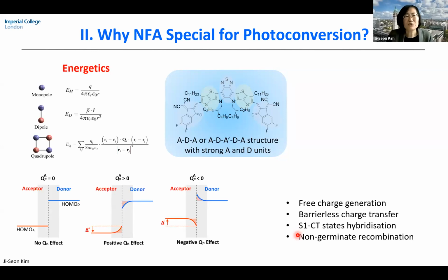But I would like to consider two main things for why this Y6 is so special. First of all, in terms of its energetics, as I mentioned before, these molecules, particularly with symmetric structure, have a negligible dipole moment. But because of the strong donor and acceptor character, we still have a very high quadrupole moment, particularly in the pi-pi stacking direction.